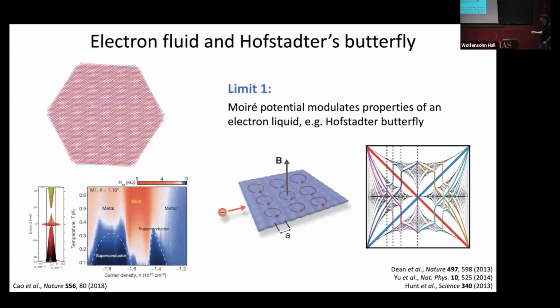Again, yesterday I talked about graphene systems, and I want to come back to this idea of different limiting cases. When you have a Moiré superlattice, you can have different regimes of that Moiré superlattice. And yesterday I talked about Hofstadter physics that comes about as an electron is moving through some periodically modulated electronic system in the presence of a relatively large magnetic field. You get a Hofstadter spectrum. It breaks up into particular subbands. And this limit you can think of as electrons moving in some weakly perturbing potential, a potential which isn't strong enough to localize them at a particular site, but nonetheless has important consequences. And oftentimes in graphene-based systems, this is the appropriate limit to consider.